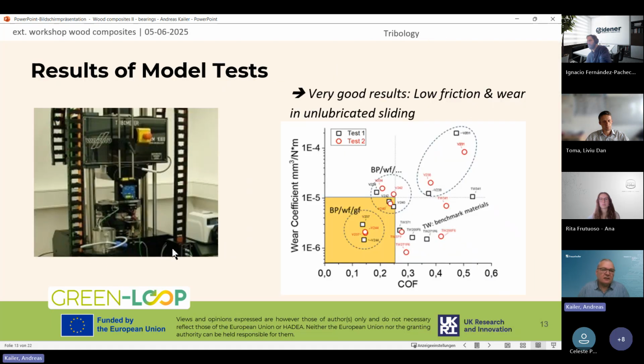So what we got here as results is shown as an overview on the right-hand side. I always thought it is best to show all the materials in this two-dimensional diagram, where we have on the one axis the friction coefficient, COF is coefficient of friction, and on the other axis the wear coefficient, which is the volume loss in cubic millimeters per sliding distance and normal force. So the lower the values, the better is the material.